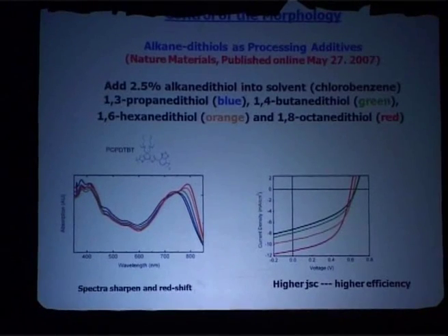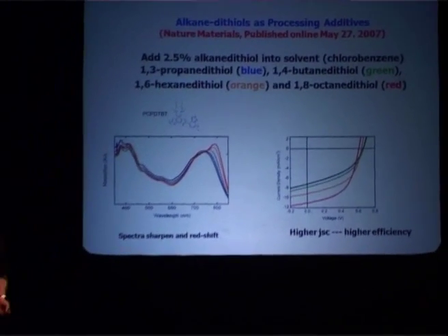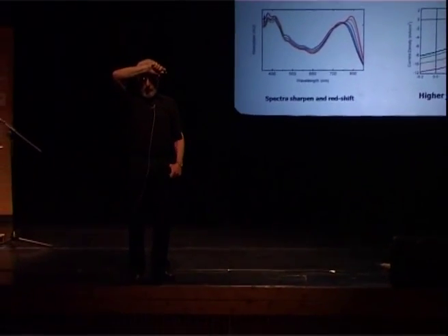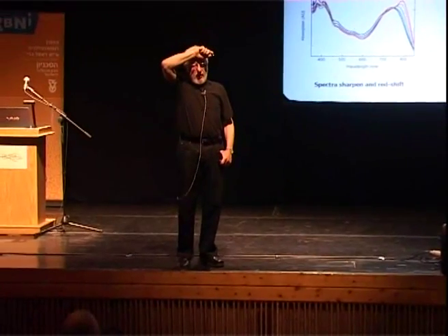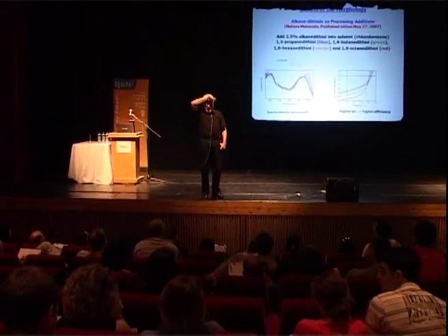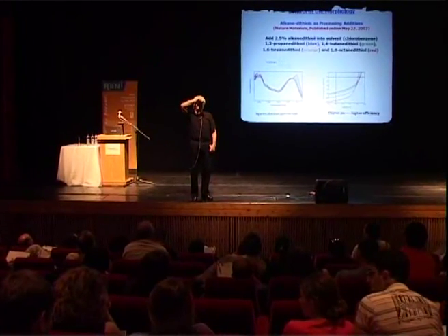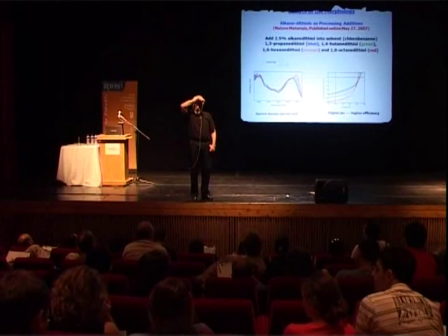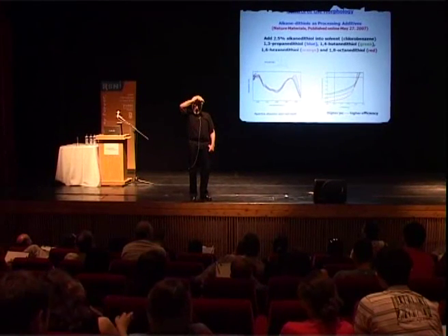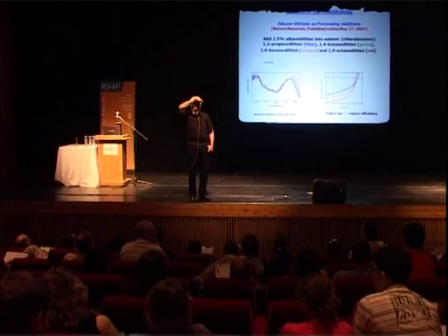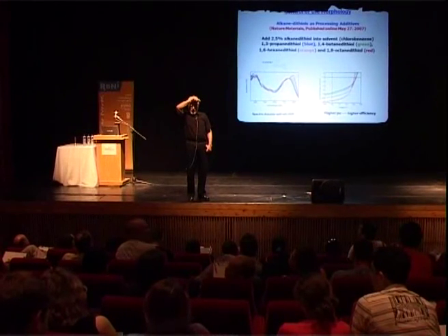All right. Sorry? Yes? Can you estimate how much of each network is really connected from top to bottom? I don't know the answer to that, but it's highly connected because I'm going to show you an example in a minute, when I get there, where we get 100% quantum efficiency. Every photon that's absorbed leads us to an electron-hole pair, and we collect them all. So they're pretty well connected. External quantum efficiency, or External.